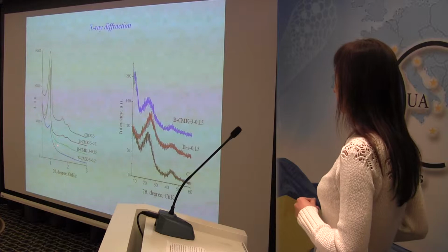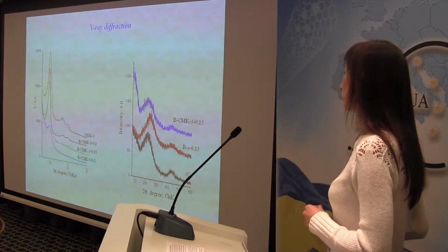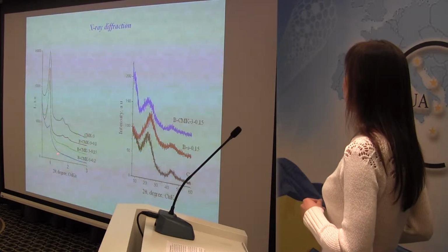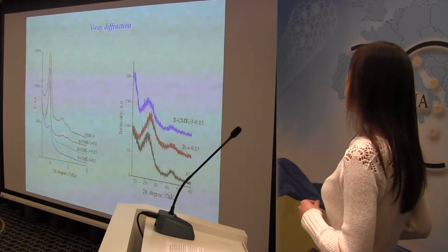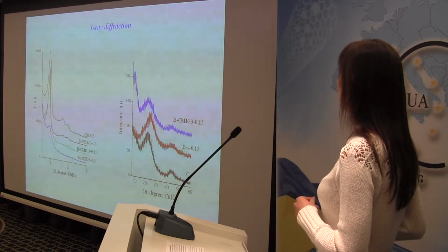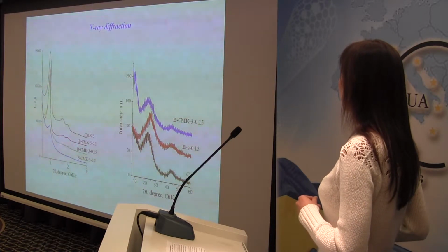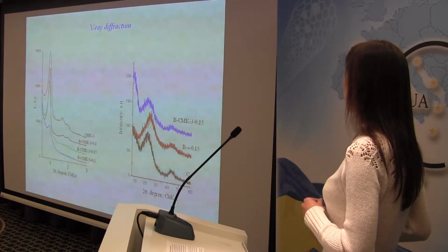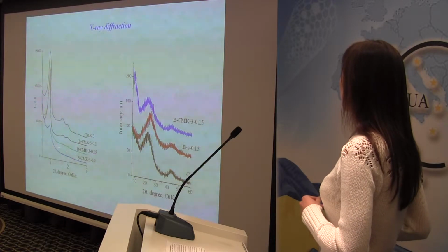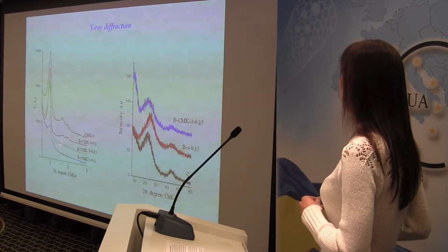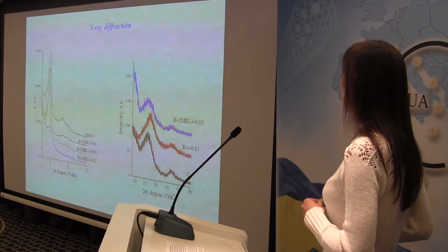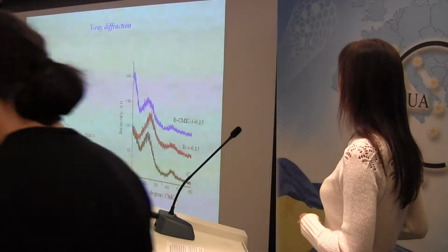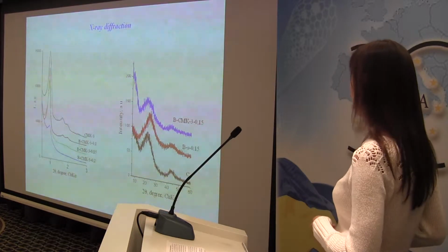With increasing content of boric acid in the mixture for impregnation of the silica matrix during obtaining of boron-containing mesoporous materials, there is a decrease of the position, a decrease of the intensity, and splitting of low-angle reflexes. The maximal used ratio of boric acid to sucrose, 0.2, leads to a significant decrease in the intensity of these reflexes, evidenced by the preservation of a single low-angle reflex of low intensity.